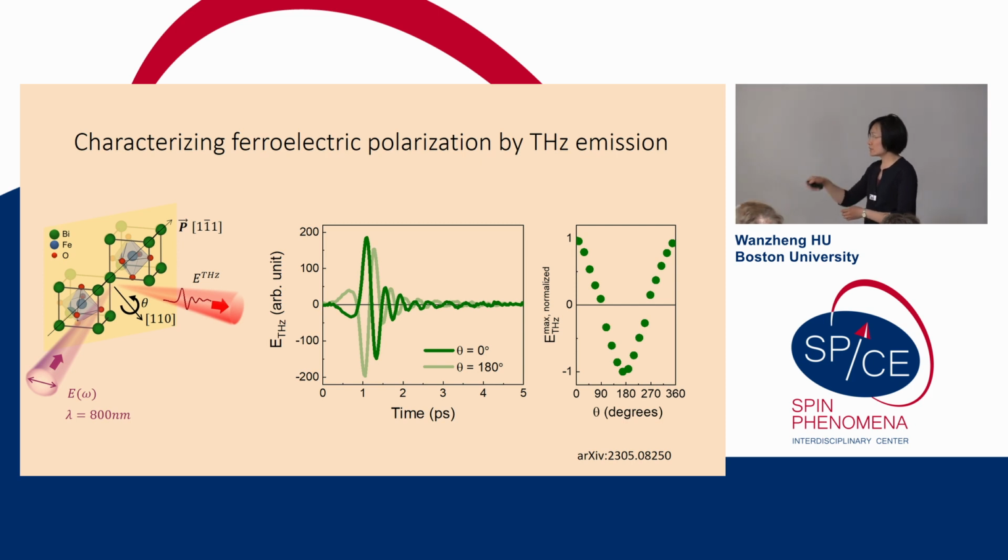While we're rotating the crystal, whenever the ferroelectric polarization is parallel to the in-plane projection of the incoming electric field, we see a large terahertz peak field. This is evidence that this material is mostly single domain. I mean, we did X-ray beforehand.